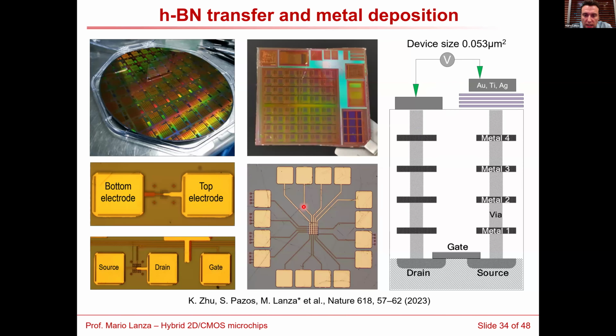Okay. And here you see the long wrinkles proving the continuity of the 2D material. Of course, there may be some micro cracks here. Okay, this is something to be considered. But in general, it's a very long and continuous film because it's multi-layer. It's 6 nanometers, so we can transfer big areas. And the big advantage is that now we can adjust the material that we want, and we can have a very small device size of 0.053 micrometers square. So as you saw in the introduction part, all the previous attempts were very large device sizes. The smallest size that I showed was 10.8 micrometers square. Here are really sizes that are similar to those in commercial memristive devices.